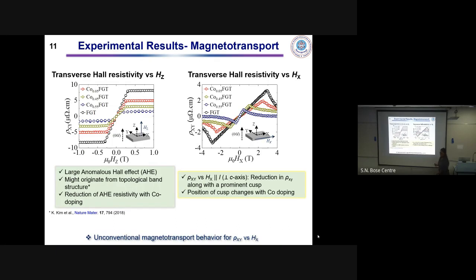Same figure. Basically, when the magnetic field was applied in the z direction, this matches with the c-axis of the crystal. So what we are observing is a saturation of the Hall resistance, and it has a component from the ordinary Hall effect and the anomalous Hall effect. But now, when the magnetic field was rotated and applied in the plane of the sample, in the x direction, that is perpendicular to the c-axis, ideally the transverse Hall resistance is supposed to go down, right? But we observe an increment in this value.